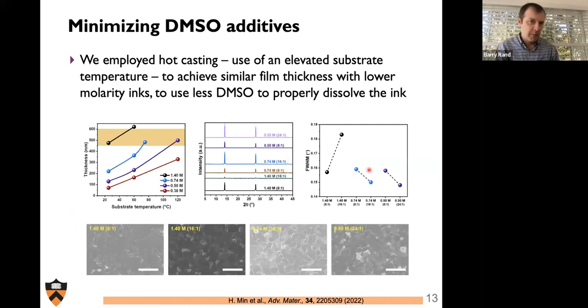So what we did in some recent work was to employ this process of hot casting. This is a process where you elevate the temperature of a substrate as you cast the film onto it. And what it does is it promotes growth of that film rather rapidly, and also allows you to access thicker films with lower molarity solutions. So what I'm showing here in the upper left is, as a function of the substrate temperature, the thickness of the film. And I'm showing it for different molarities of solution by almost an order of magnitude, from 1.4 molar to 0.3 molar.